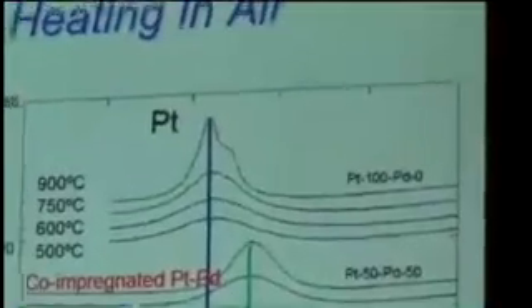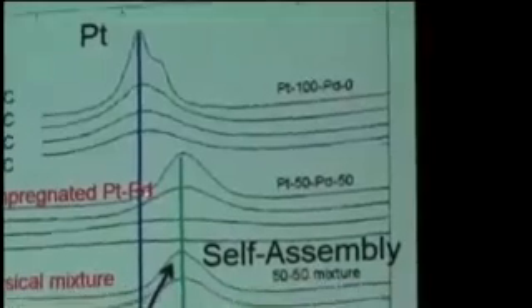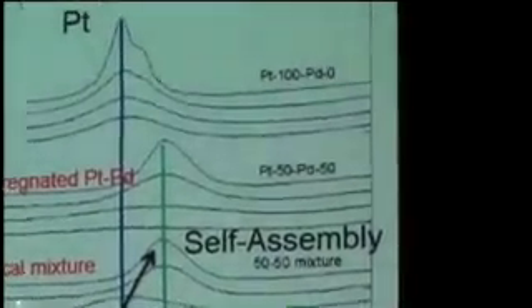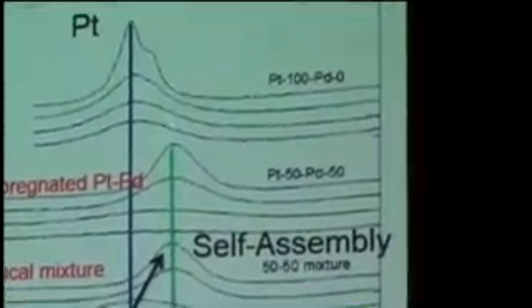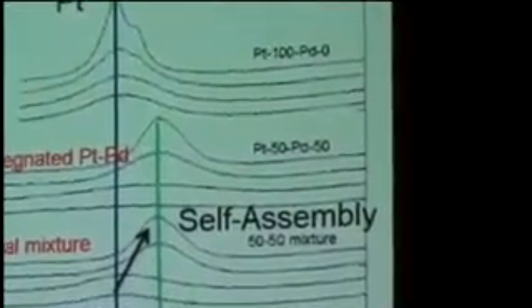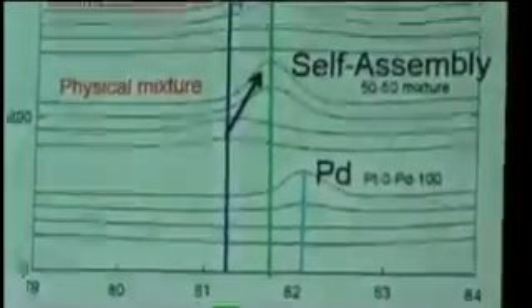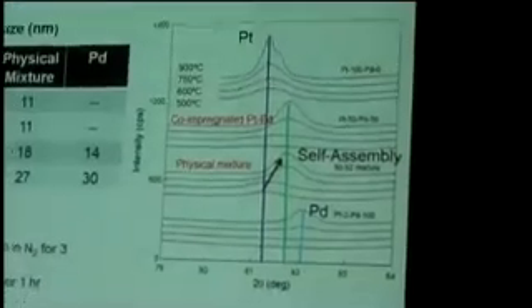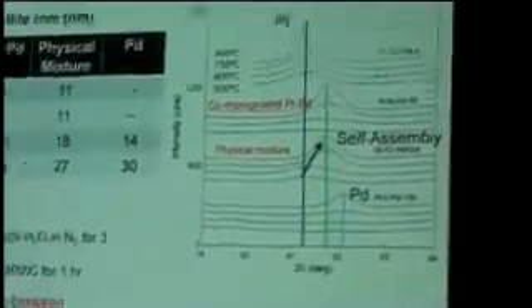What's interesting is if you impregnate platinum palladium, or you make a physical mixture, in both cases you form the bimetallic. So it doesn't matter what you do. You can mix them together, or you can just physically put them in the reactor, age it, and the peak you can see shifting from that of platinum to somewhere in between. So this is the phenomenon that we call self-assembly.